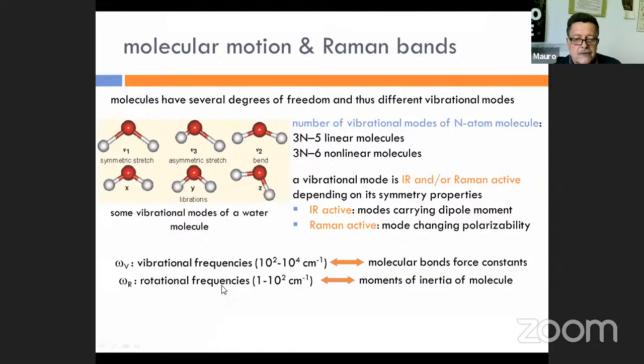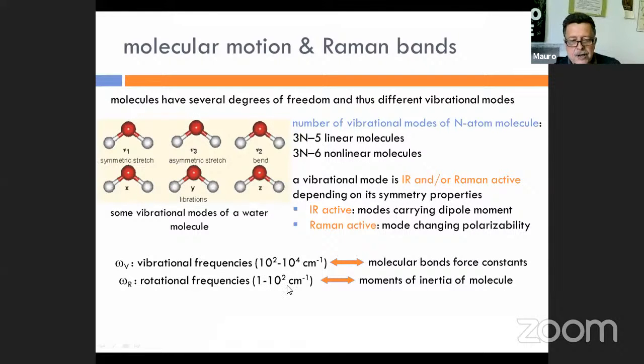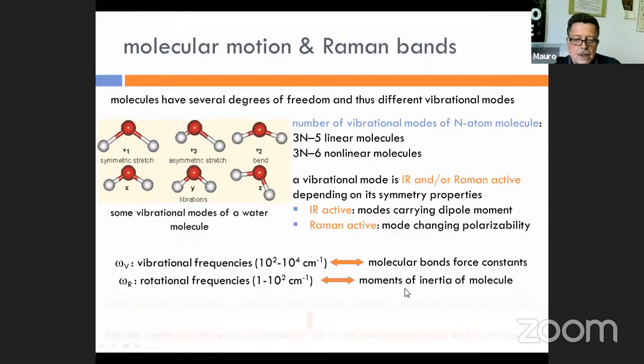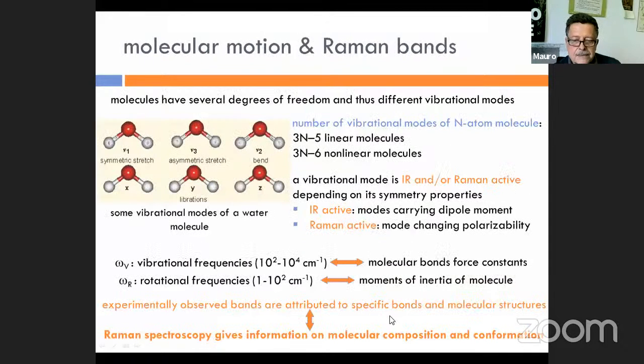While the rotational frequencies, that is the Raman frequency due to the rotation of molecules, are in a much lower energy range. Then we see that the experimentally observed bands can be attributed to vibrational or rotational modes, and therefore Raman spectroscopy gives direct information on molecular composition and conformation.